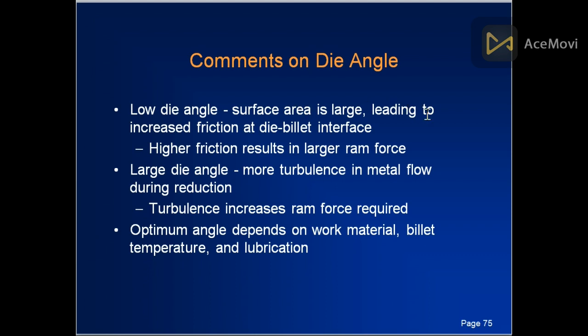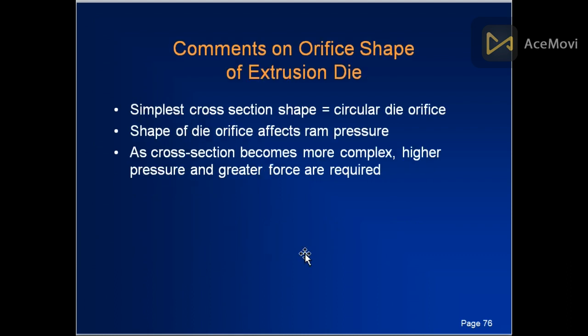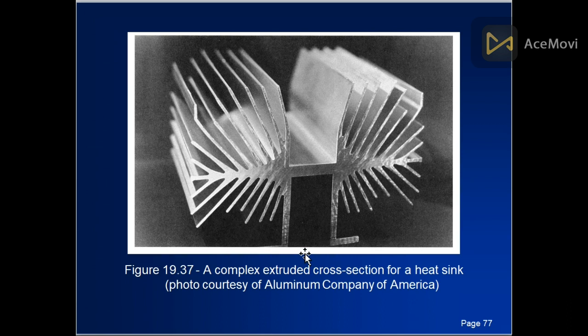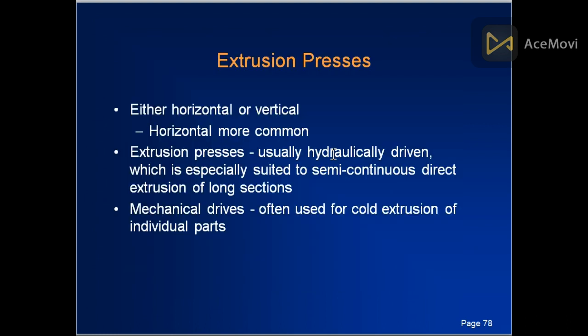With a low die angle, the surface area is large, leading to increased friction. With a large die angle, there is more turbulence in material flow during reduction, so ram force is increased. The optimum angle depends upon the work material, billet temperature, and lubrication. This is a complex extruded heat sink section, not important. We see this type of shape on bikes and engines.